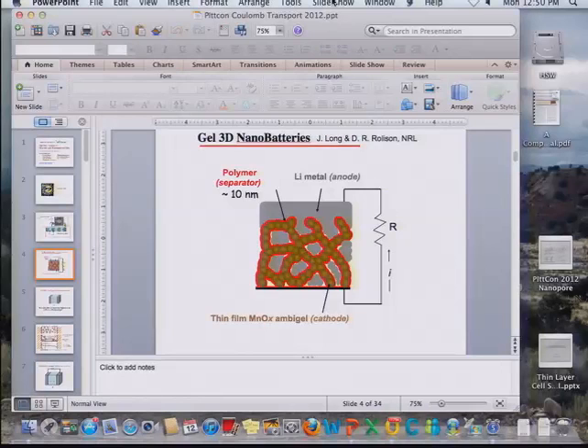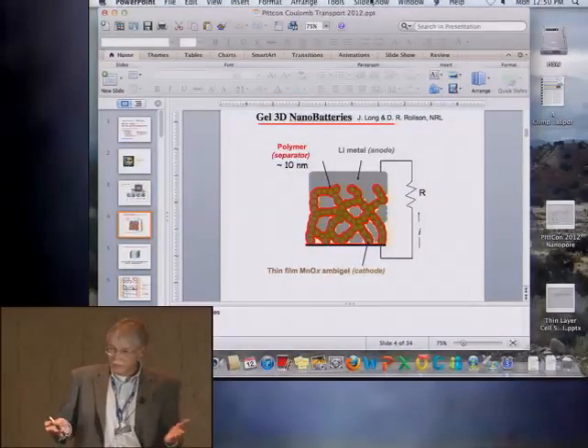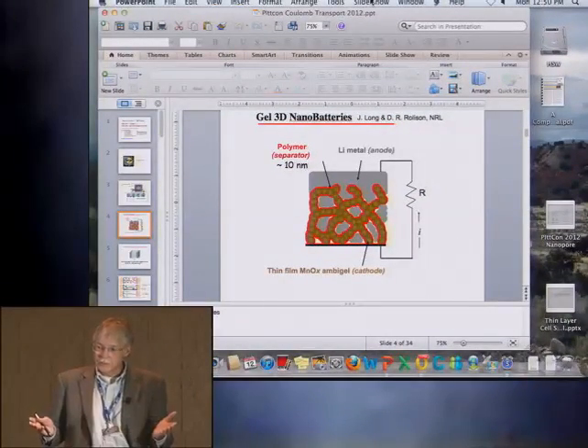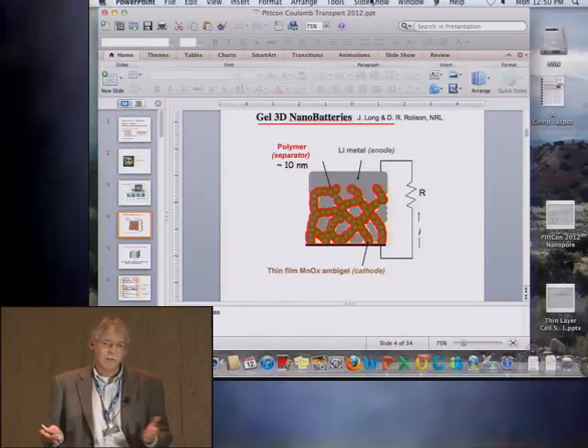And you don't have to use very conductive polymer films because they're so thin. It doesn't matter if they're resistive. The thinness gets you over that hurdle. And looking at this, I started thinking about, well, we all started thinking about this. What would happen if you really did have 2 electrodes separated by 10 nanometers? And the electrodes are charged, and the electrical fields from those charges are going to be overlapping, and they're going to influence transport, and they're going to influence the kinetics of ion insertion into the electrode materials.